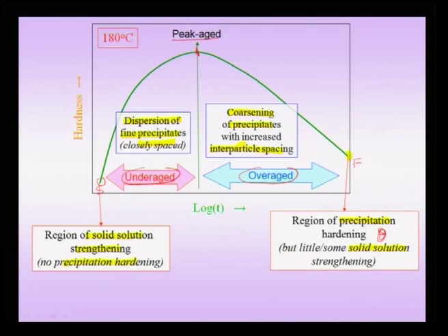So, this particle here has to be read as precipitate; we have an increasing precipitate distance. Therefore, initially we have a fine distribution of precipitates in this regime, but here these precipitates start to coarsen, and if you wait long enough, the precipitate distance would increase, but they would also get a little coarser. So, this is what is leading to a decrease in hardness after the peak hardness.